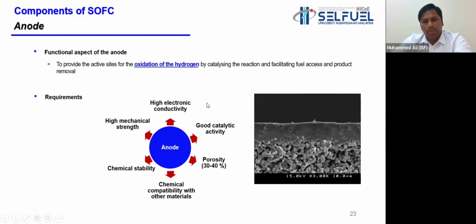Same way for the anode, it should be porous, and it should have high electronic conductivity. Here, it should not have ionic conduction. Maybe you can have minimum ionic conductivity, but electronic conductivity should be more. So what happens at the anode? It should provide active sites for the oxidation of hydrogen, and also it should provide facilities for fuel access and for the product removal. So these are the important functional aspects of the anode. And it should have good porosity, as I showed in the micrograph, good chemical stability or compatibility, and also high mechanical strength. That is the major requirement of the anode.